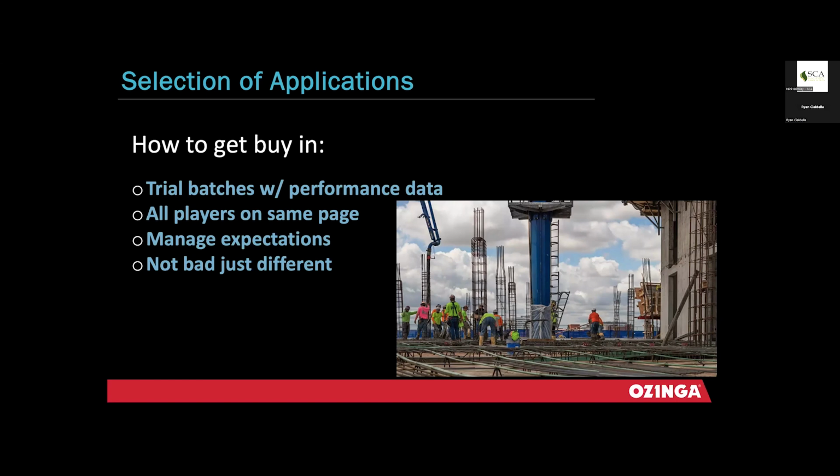The testing companies need to understand that the mixes of the past, even just a year or two ago, using type 1-2 cement with 15-20% slag, had a lot of forgiveness in them. You could potentially not put the cylinders in the cooler or store them per ASTM. But these mixes now, using PLC cements with higher replacements of slag, are more sensitive to temperature. They really need to understand that following the methods of proper curing, managing and handling the cylinders is going to become that much more important as we continue down this path, because a difference of 4 or 5 degrees could make the difference of whether it makes strength or not.